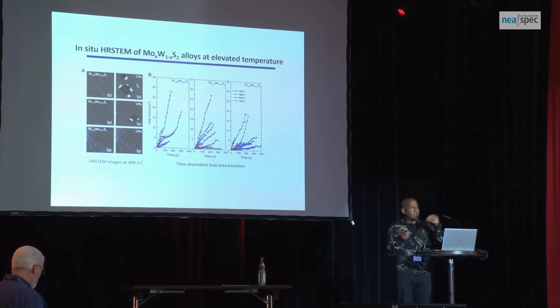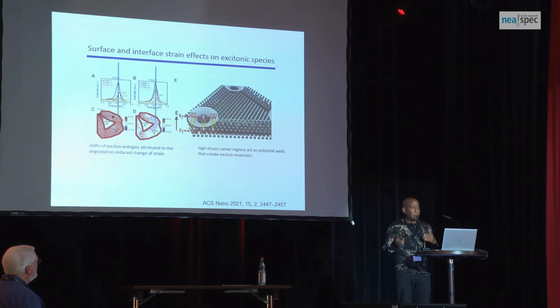If you raster scan with electron beam, what happens with highly alloyed, or the intermixing is high, compared to the one that's not alloyed? Turns out in both cases you can form these holes. The holes form as you raster scan electron beam on the sample, but the size of the hole increases over time for the alloyed region much less compared to the unalloyed, the pristine region. And you can do that at different temperatures, and you can see that the thermal property of the sample can be enhanced by alloying the sample. So the story goes on and on.